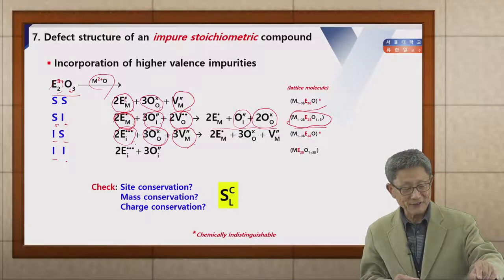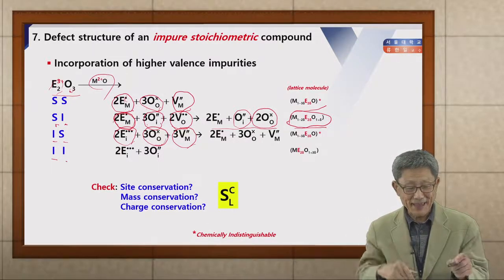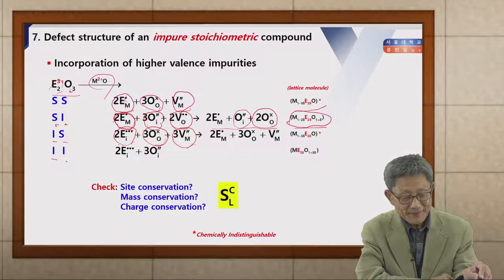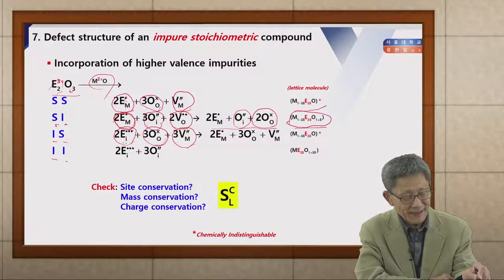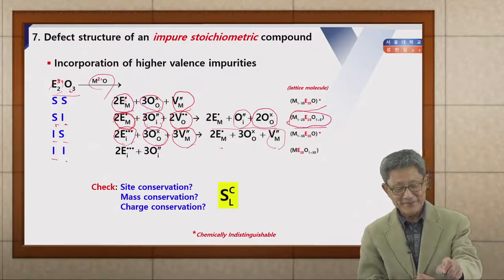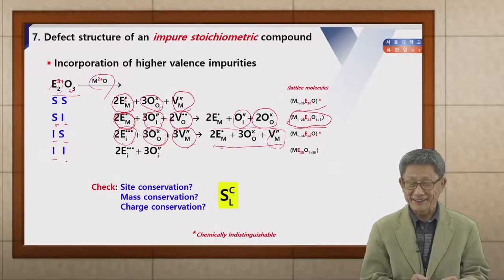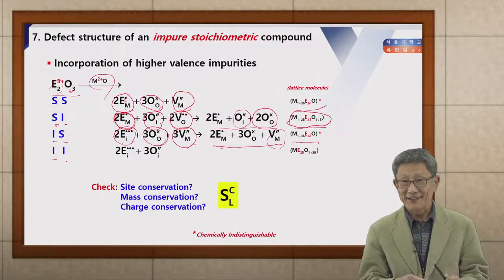Again, you can see there are too many point defects. So the possibility to lower our system energy is the following. You see, this impurity, let's say these two, go to and occupy the empty host sites to make substitutional impurities, leaving behind only one cation vacancy. This is obviously much cheaper energetically. Okay? Then it has such a lattice molecular formula.